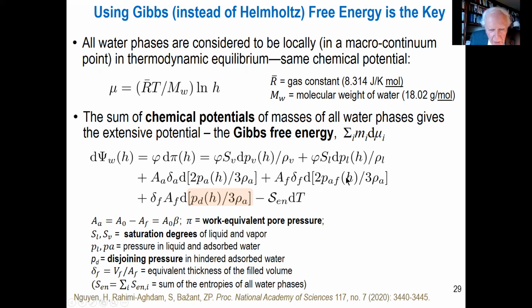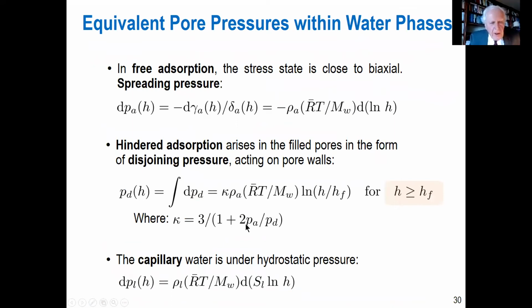Similarly for the filling of the pore, but when you get to pore pressure in pores which are fully filled, this is called hindered adsorption, and the pressure is called disjoining pressure. It is known that it typically exceeds 100 megapascal. And then we have triaxial stress, so instead of 2/3, we have 1/3. This is accounted for. If temperature is varied, this term is essential, of course, the change of temperature. So this can all be calculated. Actually, it's not terribly difficult. We have a program for this. And for free adsorption, we have the spreading pressure, which is expressed here for hindered adsorption. That sort of repeats in more detail what I just said. And for capillary water, where the meniscus radius is essential, that's here.